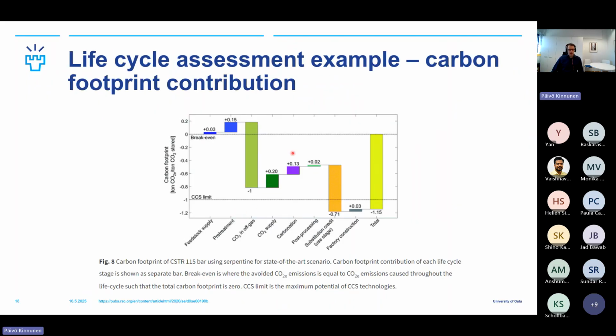And here is one example about the life cycle assessment. So this is starting from zero, and feedstock supply. You have some CO2 emissions from pre-treatment. So this is serpentine, so you have to heat treat it, and you get some penalty in terms of that. Then you get the CO2 off gas that you're storing into the material.